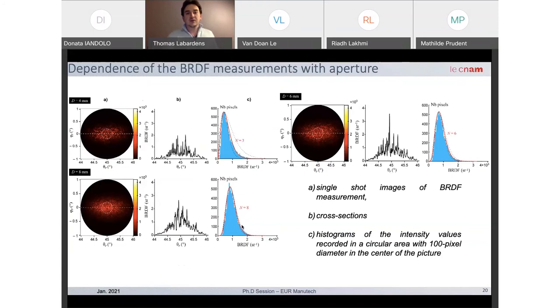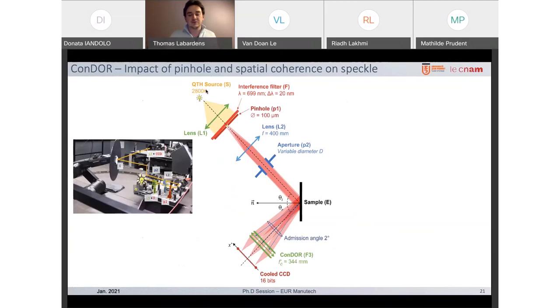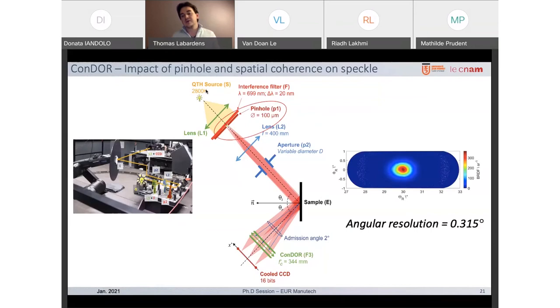But now, since we have those measurements and they are coherent with the speckle theory, we should be able to get those results through simulations. What's important to remember with simulations is that we need to take a lot of parameters into consideration, but probably the most important one is the size of the pinhole, because we need to have the impact of spatial coherence. Indeed, what limits the resolution of the system isn't the CCD, it is the size of the pinhole. When we have an angular resolution of 0.3 degrees, this is what you get. So you get the smooth image that you had in the beginning.